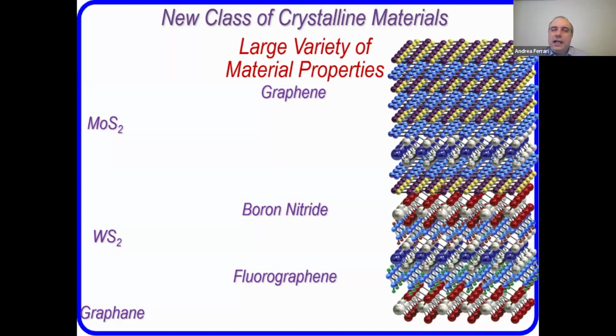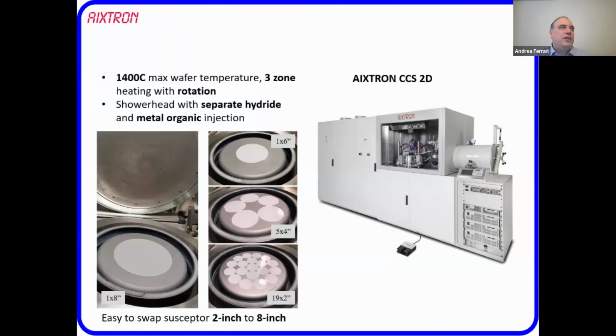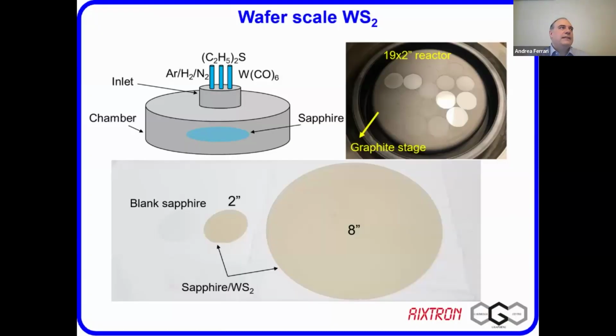Something else that happens, you can have the so-called moiré materials or moiré properties. When you have the interaction of the two layers, you can change the optical properties for emission, absorption, and many other things. And as I mentioned before, this system of Aixtron can produce samples of different sizes, but also of different materials. This is an example of a wafer-scale WS2, up to 8 inch, grown with this system.